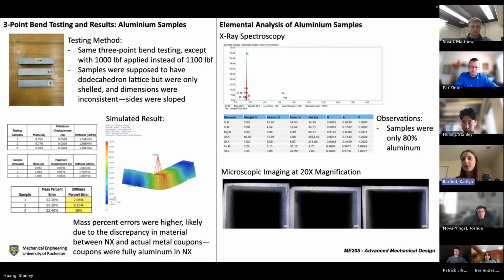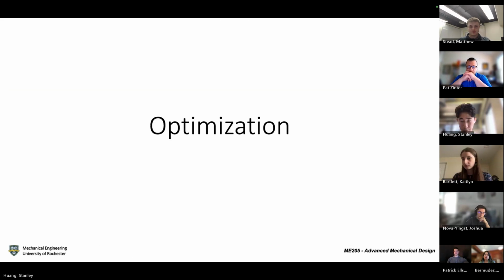Comparing the stiffness again, I got pretty decent results, but the mass percent errors were higher. I attributed that to the fact that they weren't entirely made of aluminum like we expected. But we were still getting somewhat decent correlation between the two.